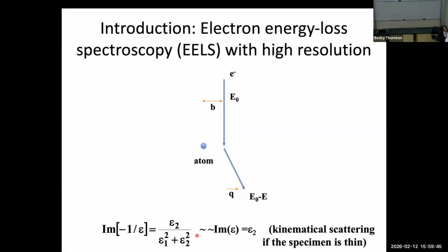But in our case, our specimen is very thin. It's only one atomic layer. So in this case, the electron can scatter only once, only once at the most. It's the same thing as X-ray or light, a kind of kinematical scattering, so there's no need to think about multiple scattering. In this case, our spectrum becomes epsilon 2. This is the same as light scattering.